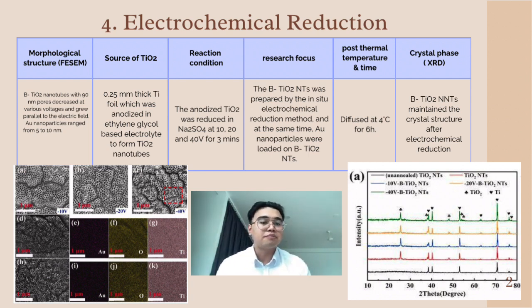Negative 10 volt black TiO2 nanotubes exhibited the greatest surface quality. The negative 20 had mild damage and negative 40 showed evident destruction in the red dotted block. Hence, current corrosion caused the nanotubes to lose a modest quantity of TiO2, damaging the surface shape.